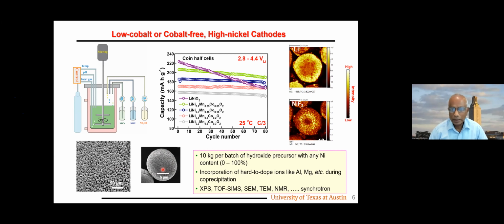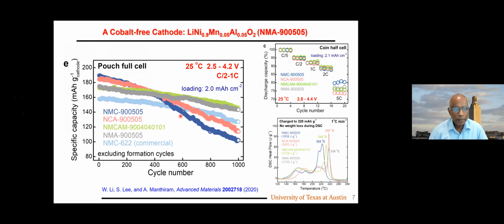And third, after cycling for a large number of cycles, we have the capability to open the cells after thousands of cycles to examine by different techniques: XPS, ToF-SIMS, SEM, TEM. And on the process, we also can use solid state NMR or liquid NMR. And if we need synchrotron, then we go to national labs in the US. Eliminating cobalt, we were actually successful in eliminating cobalt.